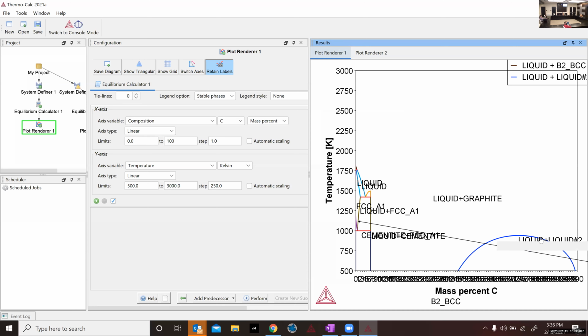So this is the liquid 1 plus liquid 2 region right here. Right, so where's the solid carbon? Do we need to zoom? We are ignoring pure graphite. Okay, that's why. And when you start looking at regions that are way outside of where normal people would look, or when you start suspending the equilibrium phases, this brings up a good point to consider in ThermoCalc. The way the databases are constructed, sometimes you can have false miscibility gaps, or miscibility gaps over here, because in reality, nobody's ever going to look at iron-carbon at 700 degrees Kelvin way out here at 80% carbon, right? So there is no experimental data way out there.